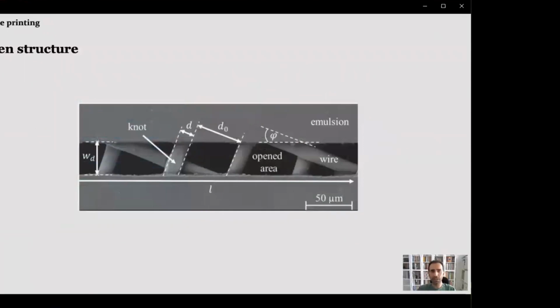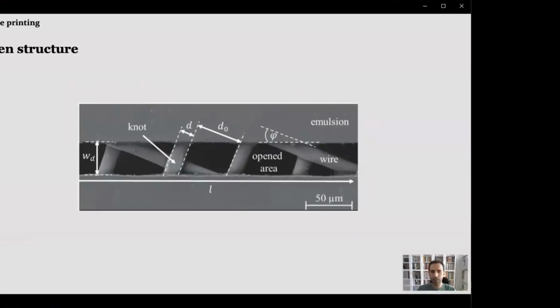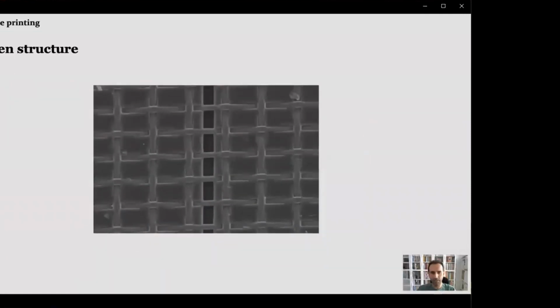So those wires are there to give the strength that the screen needs when the squeegee pushes the paste through those openings. This mesh structure can affect the contact through the mesh count, angle, how many knots in the opening of the screen. The effect is called mesh marks that increases the grid line resistance. The angle should be optimized so that there are fewer knots in the openings. Tettner and his group from Fraunhofer have some findings that 35 degrees is the best because when the degree is right, there are minimum knots and the mesh marks are kept minimum. To overcome this issue and optimize the screen, there are studies on screens with no knots called knotless screens.